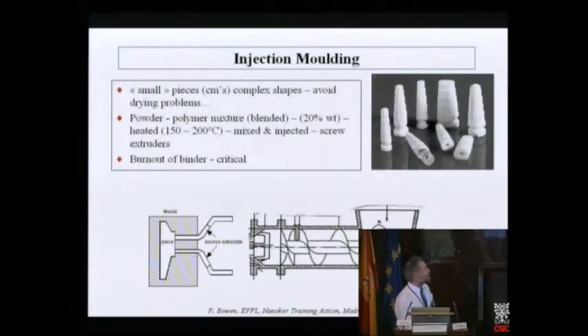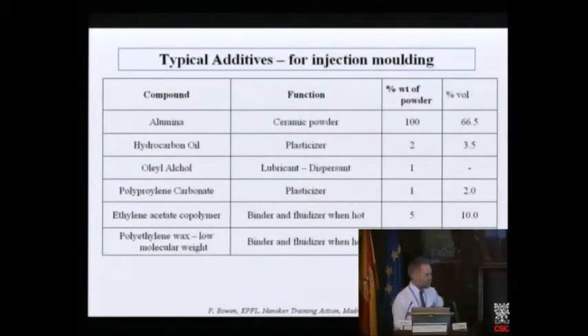So, these are the type of pieces we can make, very complex shapes, very difficult to make by any other method. What do we put in? For a typical formulation for alumina, we use an oil as a plasticizer. Things have to move. We have these ceramic particles. We have to avoid friction between the particles, so we need lubricants. The oleyl alcohol can also act as a dispersant. So another plasticizer, we have our binder, a fluidizer when it's hot. And so we can see we have a big series of different components.